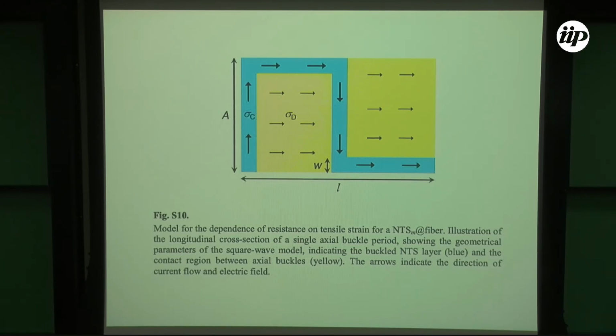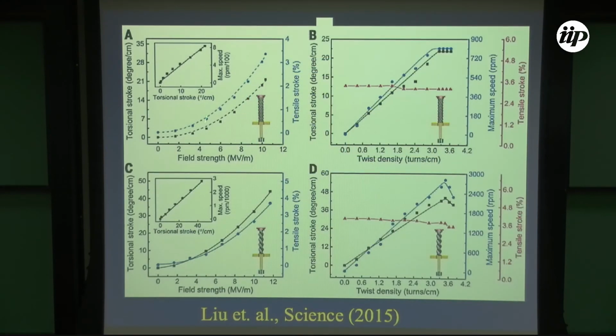Because you have this yarn, and this yarn contains millions of structures, even when we stretch them, the contact between the nanotubes is never lost. So even when you stretch and change this, there still remains a path where the nanotubes are connected. The current flows where the resistivity is lower, so you can explain why this happened.